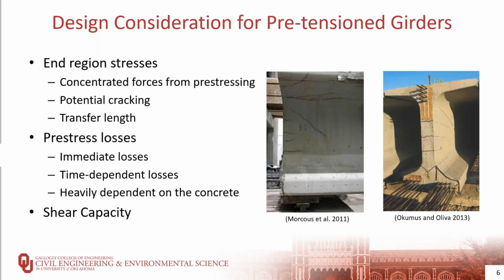Some that have been concerns of the Oklahoma DOT, as well as around the country, include the fact that the high forces and concentrated stresses in the end region of the girders can lead to potential cracking, affect the pre-stress transfer length, potentially open the girders to some durability issues. Additionally, pre-stress losses from immediate and time-dependent deformation play a key role in service and strength level behavior. And then shear demand is going to be high in the end region of the beams, and the shear capacity in that end region is going to be affected by the pre-stress and potentially is changing over time.